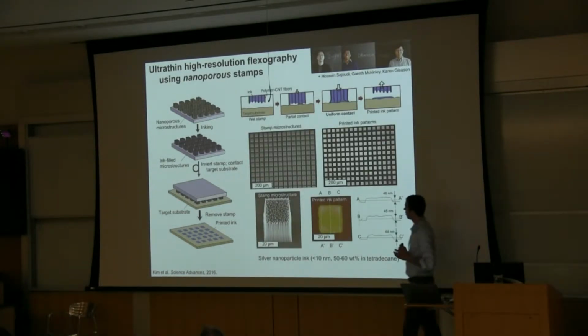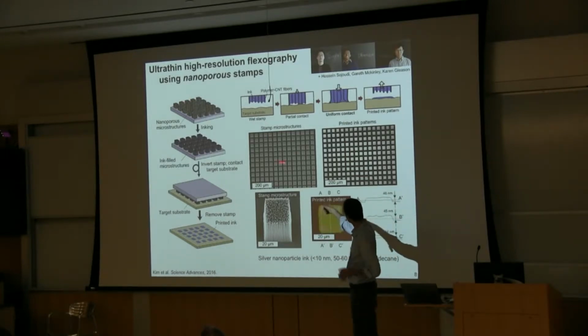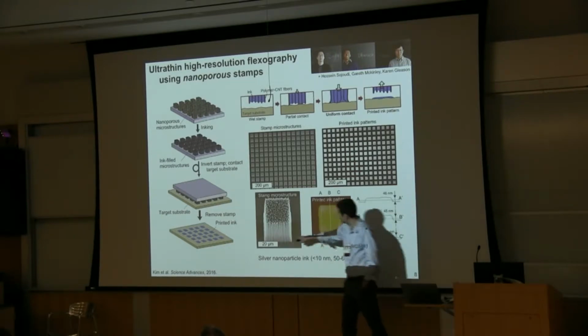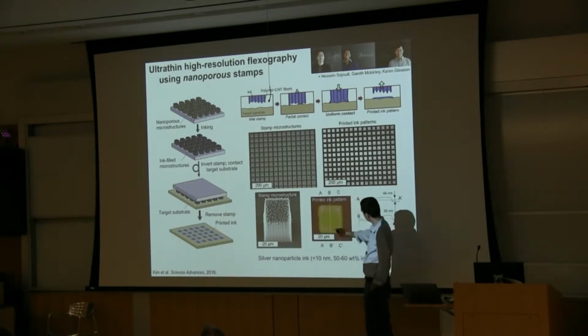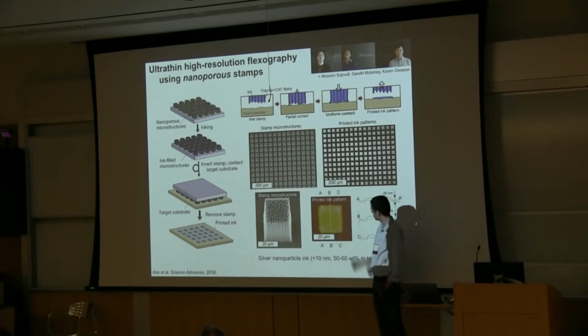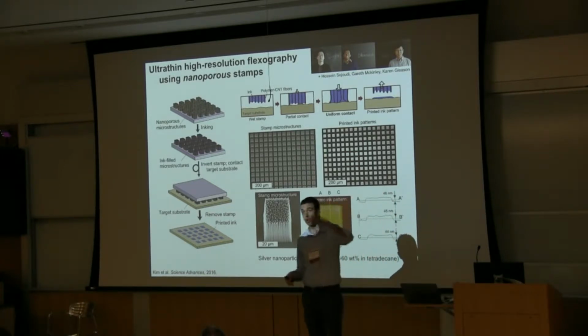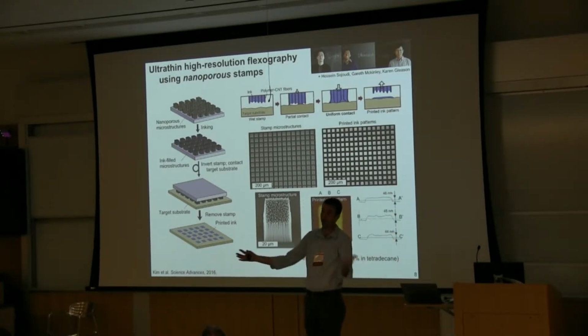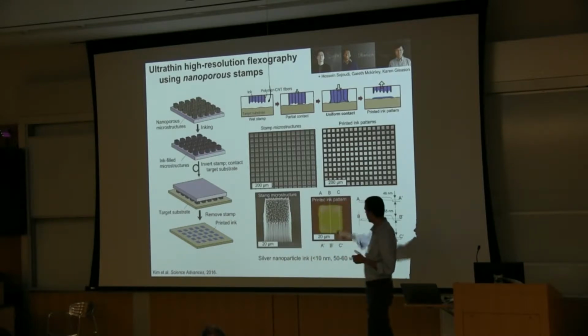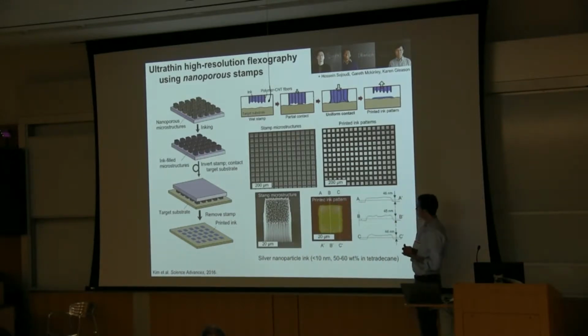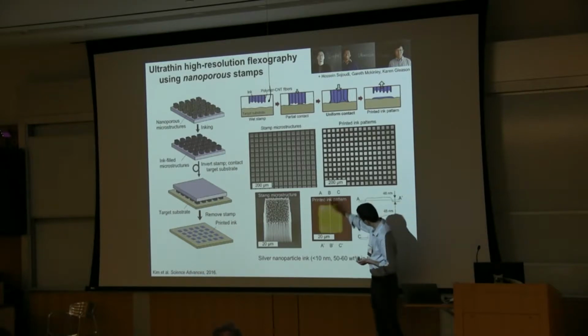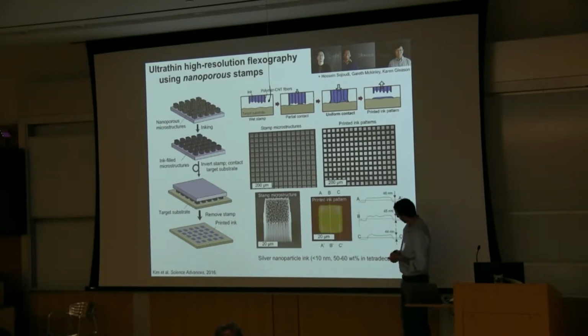And here's a very simple demonstration pattern, an array of square stamp microstructures and an array of printed ink patterns. And if you have one stamp microstructure, this is a little forest, as we call it, of carbon nanotubes, you can print a square ink pattern, in this case 20 by 20 microns on a side with relatively sharp corners. And if you're familiar with, say, the limitations of inkjet printing, where you print round droplets and they spread out and they recoil and they dry, you can't easily print square features from liquid. And in this case, if you scan an AFM across the surface of this feature, after drying, in this case the silver nanoparticles, you have fairly good uniformity.